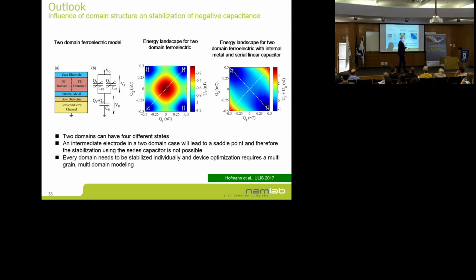And this is just a very preliminary result where we have made a very simple calculation. In most demonstrations of negative capacitance field effect transistors, you will find that people put an internal metal electrode because they want to make the potential across the ferroelectric homogeneous. But if you do that, and if you do your energy landscape, if you assume now you have two ferroelectric domains, all of a sudden you get 4 stable states, of course, because you not only have the ones where both point up or both point down, but you can also have the two in the opposite direction. And if you do the stability calculation, you find out that there's a saddle point here. So actually you cannot stabilize it that way.